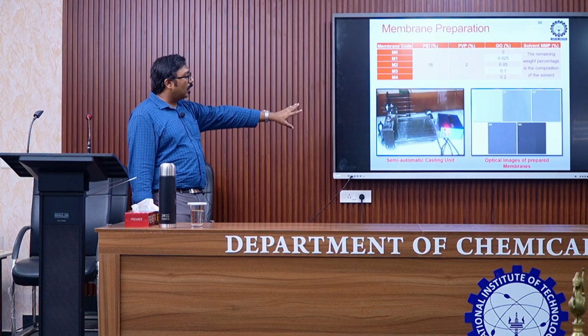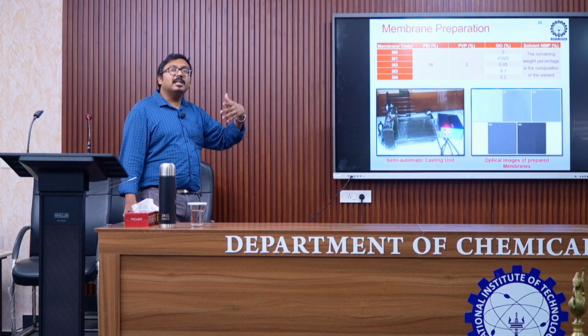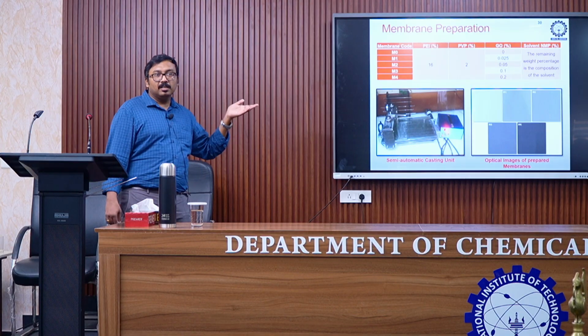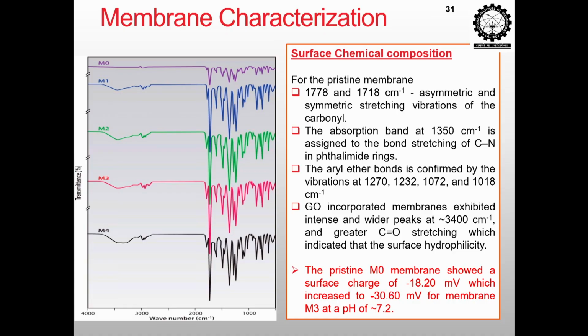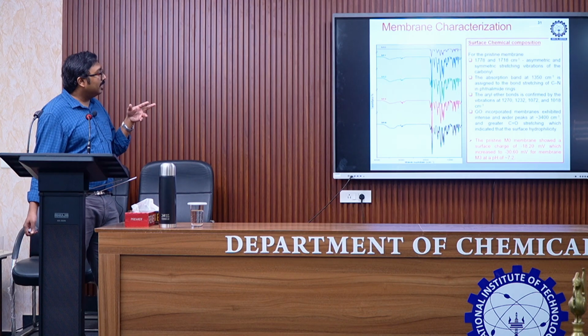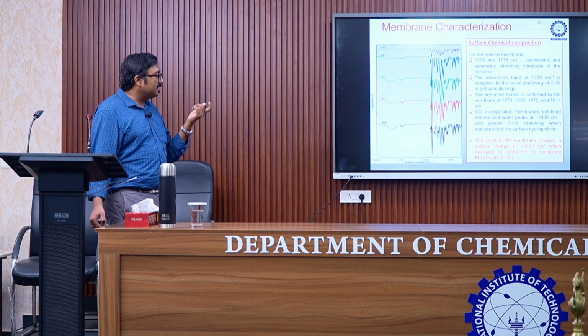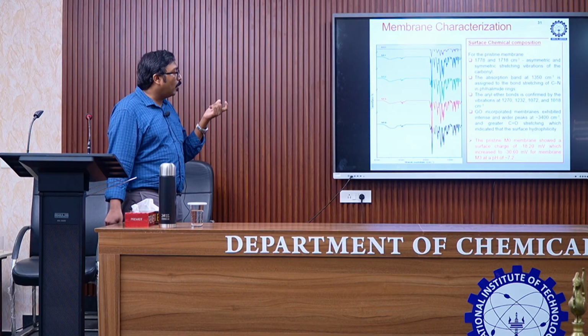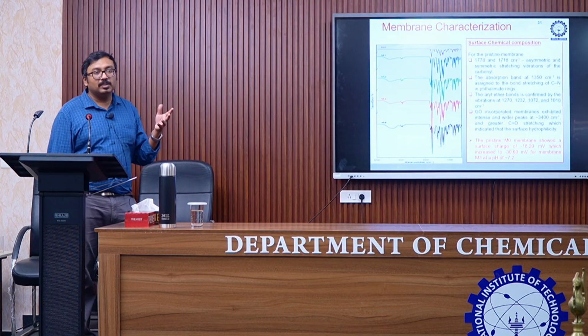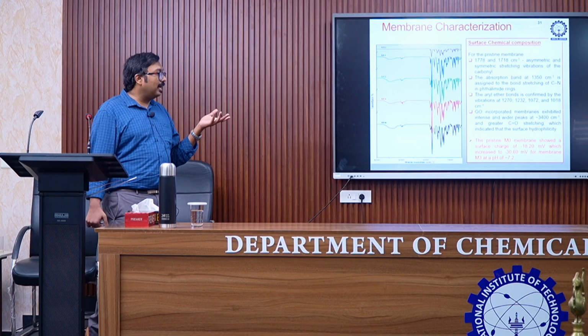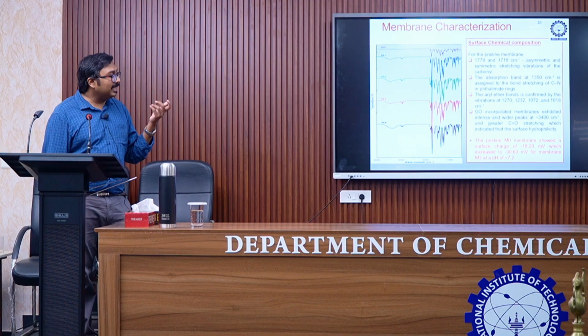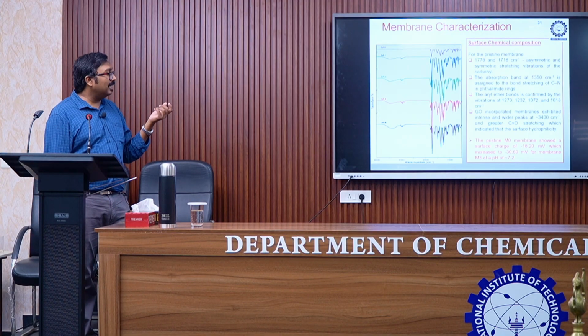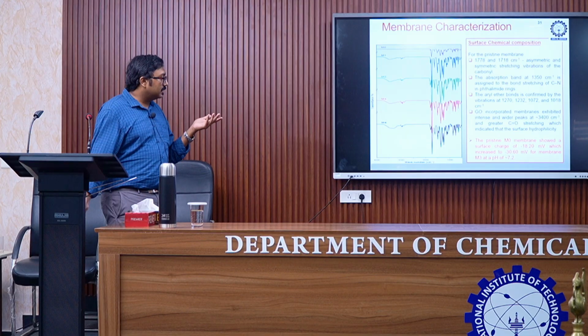and you can see these optical images of the membranes. As the concentration of graphene oxide increases, the membranes become much darker. Again, we want to confirm that it has been successfully incorporated, so the membranes have been characterized by FTIR. Interestingly, when we added the graphene oxide, the surface charge has become more negative at a pH of 7.2 or 7.4, which we ideally use for hemodialysis. More negative surface charge would indicate that the negatively charged endotoxins could also be rejected by electrostatic force.